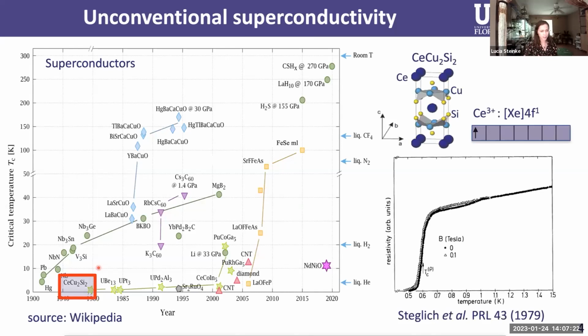And then it came as a big surprise when in 1979, Frank Steglich discovered superconductivity in cerium copper two silicon two, which is a paramagnet. It has magnetism arising from the unpaired f electron in cerium, but yet it shows a clear superconducting transition seen in the resistivity dropping to 0 at 0.6 Kelvin. And that was really surprising because it's a magnet, and because cerium copper two silicon two was so different from all the known superconductors that at the time, it was deemed the first unconventional superconductor.